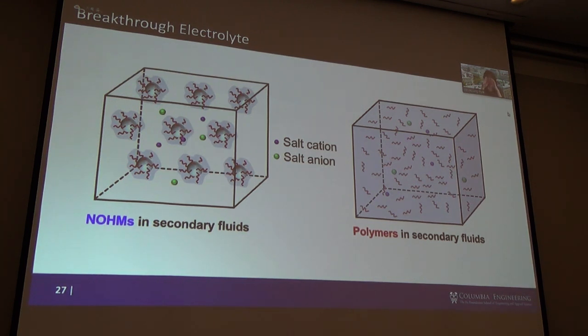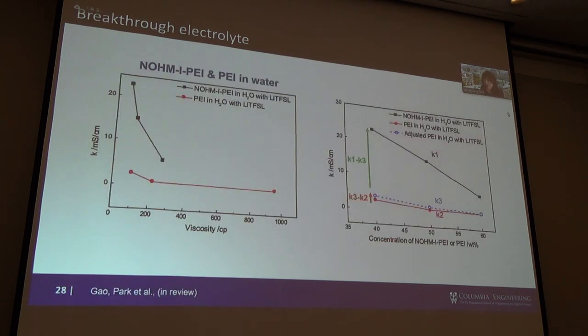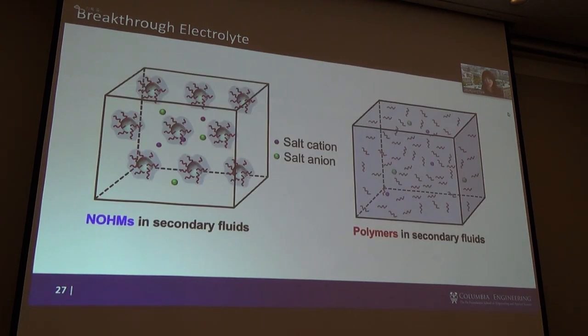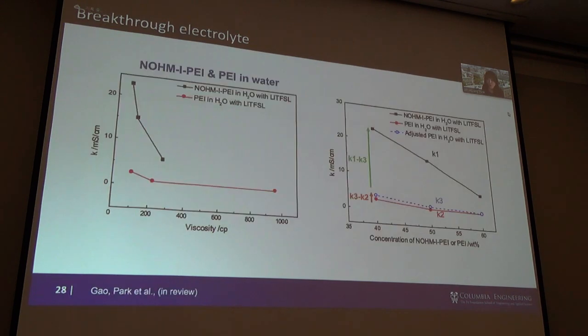So this is the picture of two electrolyte systems. One is the untethered polymer system, and the left-hand side is the NOM system. The only difference is the same polymer: one is tethered, the other one is not tethered. At the beginning, I really thought that the untethered system would have better conductivity and lower viscosity. But we keep getting really interesting data in the lab. We keep getting that the NOM-based electrolyte had lower viscosity and higher conductivity. So we were getting really confused, because if you look at the system on the left-hand side, for the same concentration of polymers, we have a lot of nanoparticles, which are a solid phase, running around. So we were getting confused.